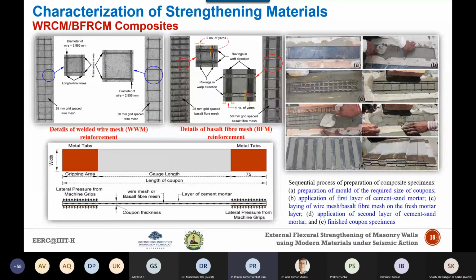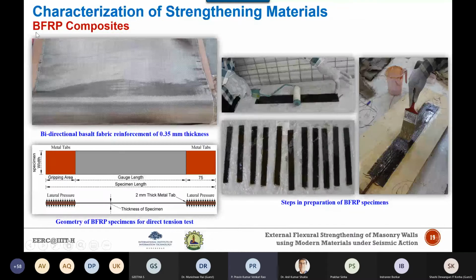And last is the fiber textile, which has been used in conjunction. Here you can see this wire mesh and the fiber mesh has been used in conjunction with the inorganic matrix, that is cement sand mortar. Whereas in case of the FRP, fiber reinforced polymer composite, we have used the epoxy resin and the hardener. So similar types of specimens have also been provided. The only difference here is an organic matrix rather than an inorganic matrix. So a bidirectional fabric of 0.35 mm thickness has been used, and similarly the metal tabs have been anchored to the ends of the specimen.